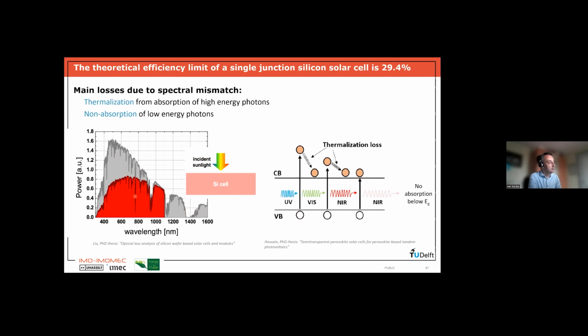Why is that? If you have, for instance, a blue photon that is absorbed, it will create an electron hole pair. An electron is excited into the conduction band, it has a pretty high energy, but it will lose almost instantaneously a lot of that energy by thermalization losses, in the form of heat, and it will relax to a lower energy state in the conduction band. And so this is the reason why we lose all this gray area here.